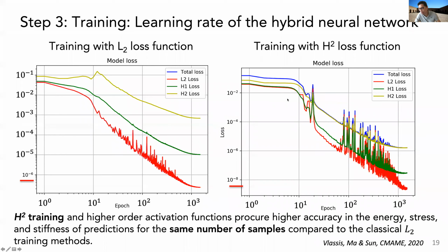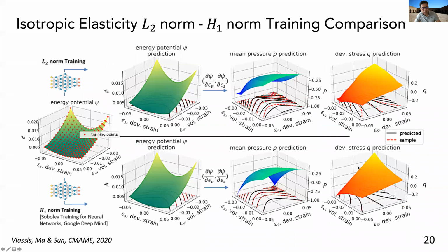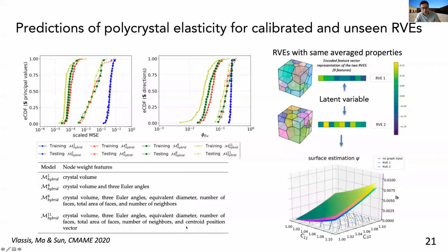So this tells you that higher order training helps us get accuracy not only on the energy itself, but also on the stress and stiffness, which are the first and second derivatives, and it even gives us more accurate energy. This is a benchmark test with pressure-dependent plasticity. You can see that for the L2 norm and the H2 norm, even though the energy landscape looks very similar, with the gradient and the second derivative the predictions are much more accurate. This is important for implicit finite element methods that require tangent calculations.